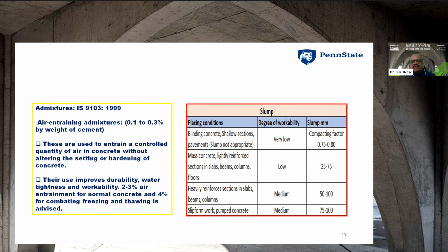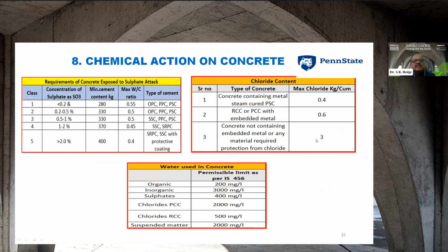So it's very important. And if you see the other table, what should be the slump? For the different placing conditions: blinding concrete, shallow sections, mass concreting, heavily reinforced sections, slipform work, etc. And the degree of workability is also mentioned. What should be the slump and compacting factor has also been mentioned in this table.